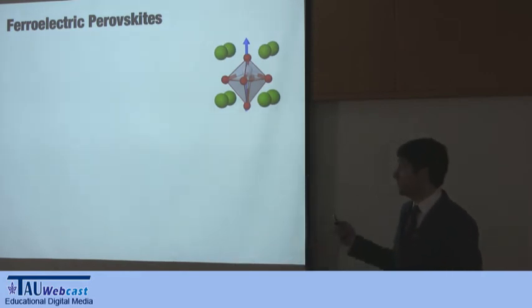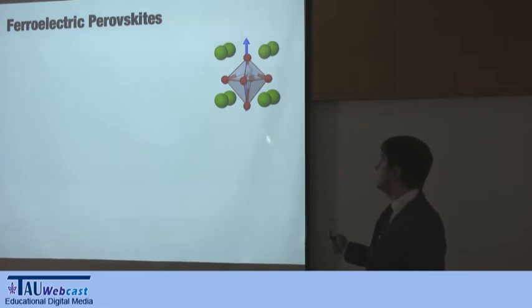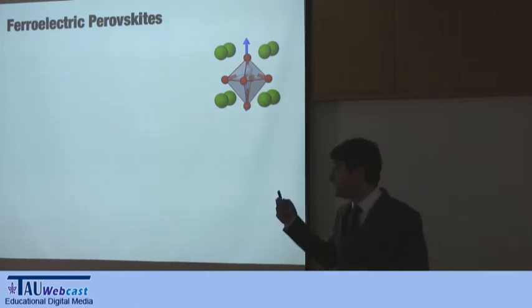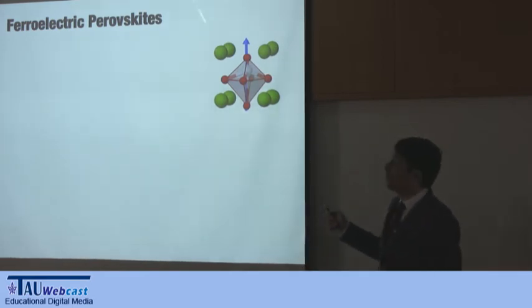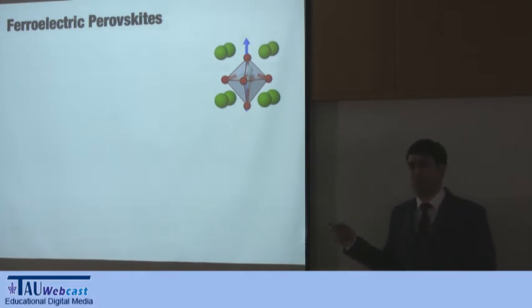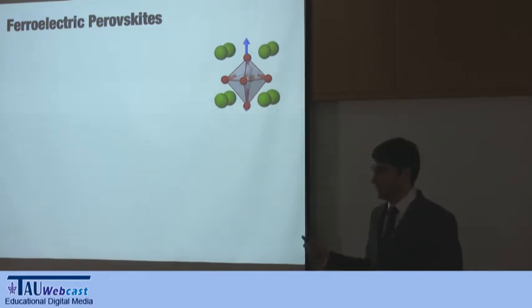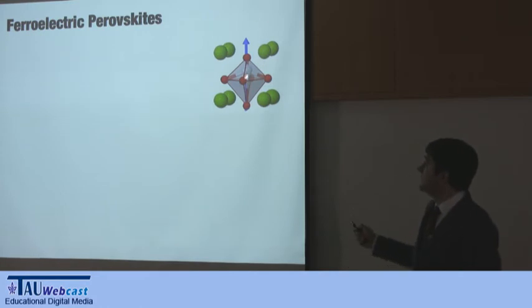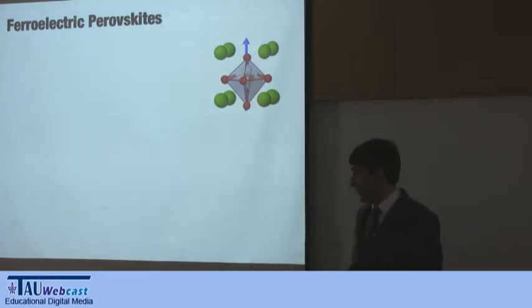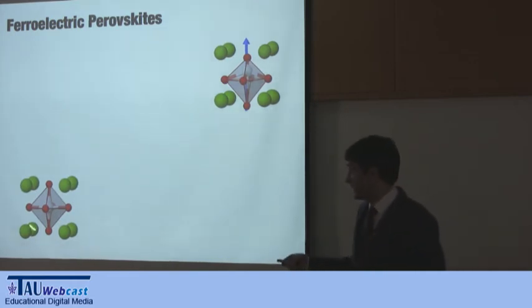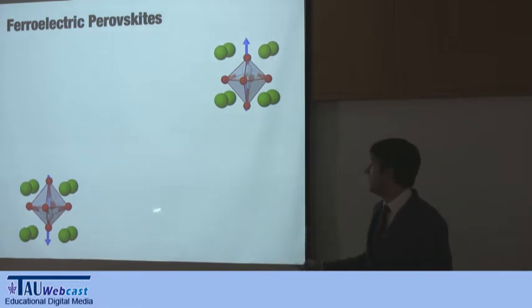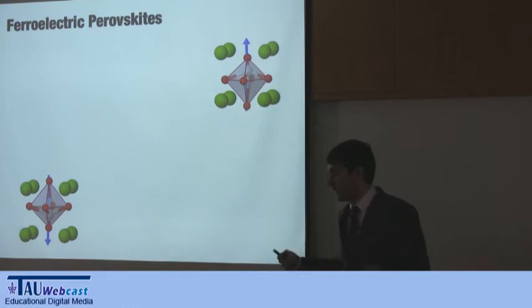Most of the time, what you have is a distortion of this crystal structure. So either the cations move along some direction, like this one that moved along the z-axis if you want, or the octahedra distort, like this case, or they rotate. When the atoms, the cations, move along one of the directions, the material is not center symmetric anymore. You have an asymmetry in the charge, and you have a polarization. This is an electronic polarization. This is the equivalent of a dipole moment, if you want, in a molecule, but for a solid. Okay? So in this case, that atom went up and created a polarization in that direction. By symmetry, you can have exactly the same thing, but it can go down. So these are polar materials, those that are non-center symmetric.